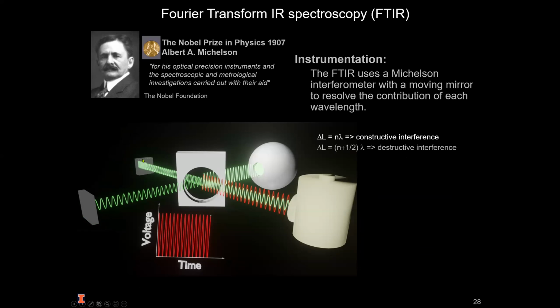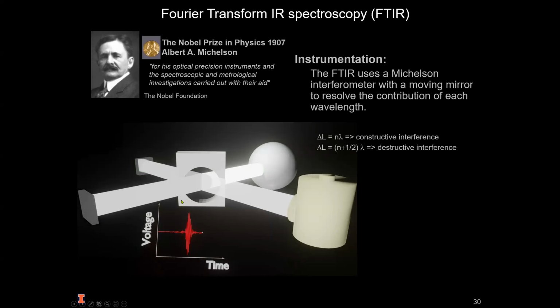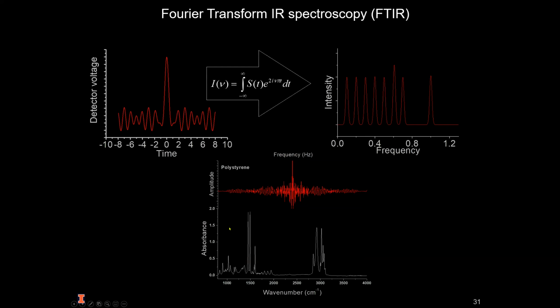For each given wavelength, depending on the position of the mirror, we will have constructive or destructive interference, causing a rise or a drop in the detector signal. Different wavelengths will interfere differently for given positions of that mirror. So when a broad range of wavelengths passes through the interferometer, the sum of the contributions of all wavelengths will result in a signal with multiple different frequencies, which combined form what we call an interferogram. When we apply a Fourier transform to this interferogram, we recover the frequency domain spectrum.